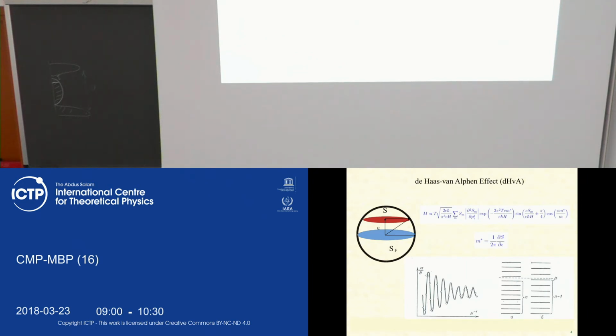Another way to measure the effective mass is the so-called de Haas-van Alphen experiment. We discussed the behavior of electrons in a small magnetic field and the diamagnetic response associated with the quantization. However, one can also discuss the behavior of magnetization in a high magnetic field. Then one can see oscillations with a period inversely proportional to the magnetic field. Analyzing these oscillations provides information about the effective mass, which is associated with the maximum cross-section of the Fermi surface. This is yet another way to test the Fermi energy.